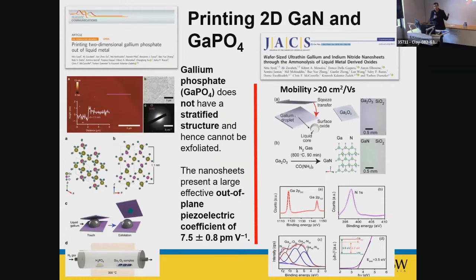Or gallium nitride, famous material for making blue LEDs. Everywhere you are using it, in your mobile phones and also displays in front of you. So this time we use a precursor that has nitrogen, urea, 800 degrees, transformed to gallium nitride. Mobility is very high, and we use it for making some devices, which are not shown here. Another example.